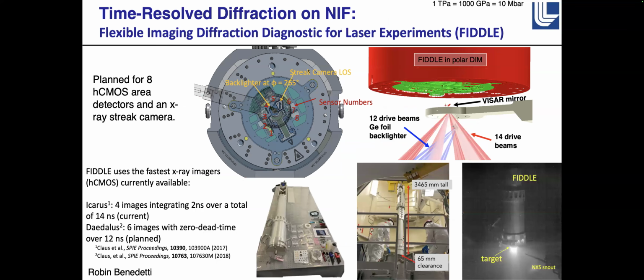So crossing our fingers. We've also developed time-resolved diffraction on NIF. So NIF can drive, we've done drives up to 90 nanoseconds using the NIF by stacking pulses. The NIF lasers have 30 nanosecond drives. The FIDDLE diagnostic uses Icarus detectors, which are HCMOS detectors that are built by Sandia National Lab. We put 8 of them. Well, so far there's only 5 of them in a target. The reason that this container is so big is because there's a lot of electronics, and these can sample every 2 nanoseconds. So they turn on for 2 nanoseconds, turn off for 2 nanoseconds, and we can measure time resolved for 4 frames of diffraction.